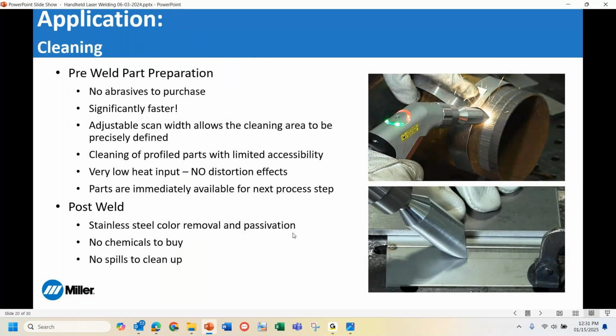The handheld laser systems typically also have a cleaning component to them. So this can offer quite a bit of benefit to an operation over conventional cleaning processes. There's both cleaning that you can do prior to welding on the components or the parts, and you can do cleaning post-weld, so coloration removal, for example. So the pre-cleaning of the part prep, if you have a component that has some rust or scale on it from sitting for a period of time, we can actually just switch the nozzle of the laser delivery apparatus and switch the mode, and easily clean or strip that rust off of those components.